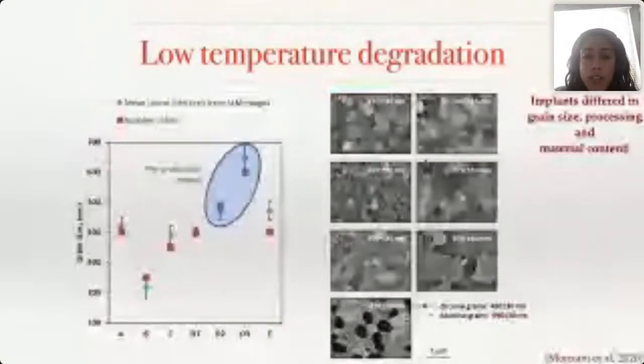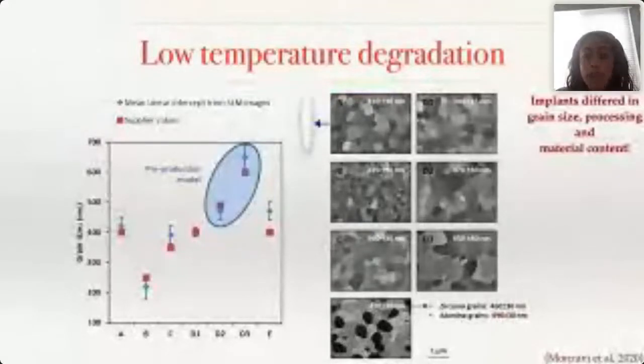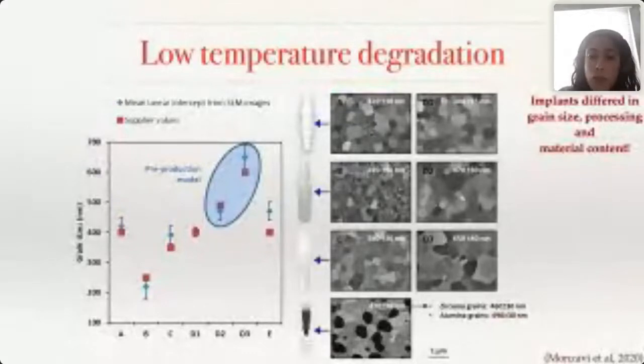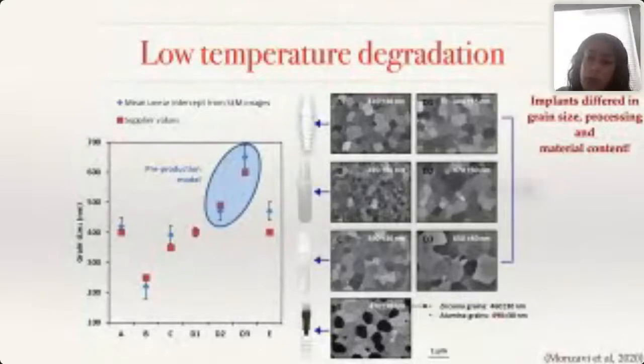These are the cross-sectional cuts of the different materials. It shows how different each implant system is, even though they are the same material. We had different grain sizes of the zirconia for each group. For example, Straumann had much smaller grain size, and with Tab Dental we had some of the largest grain sizes. Zeramex had these alumina grains. So these are all zirconia implants, but with different properties because of the way they are manufactured.